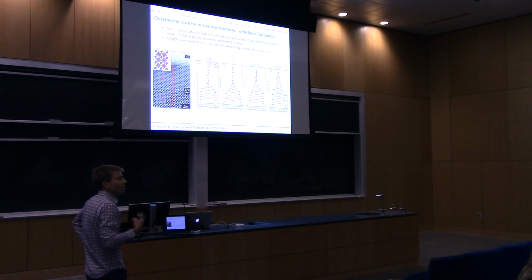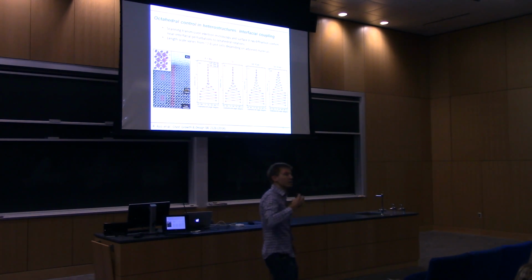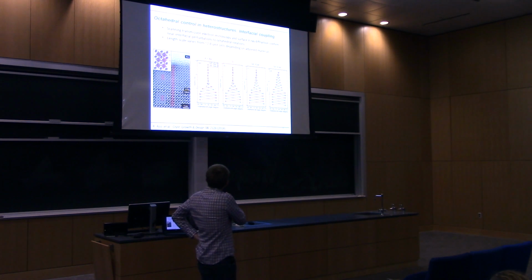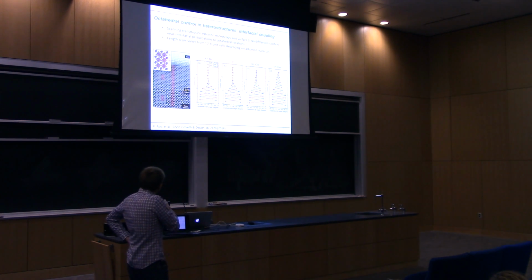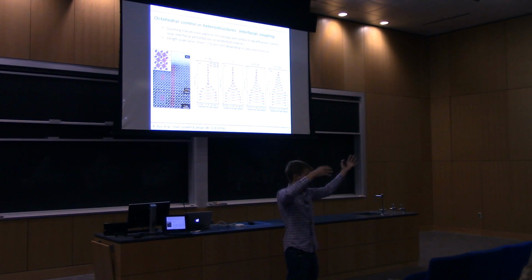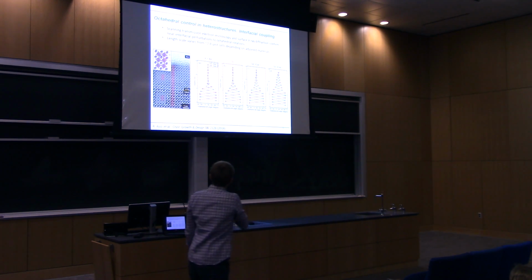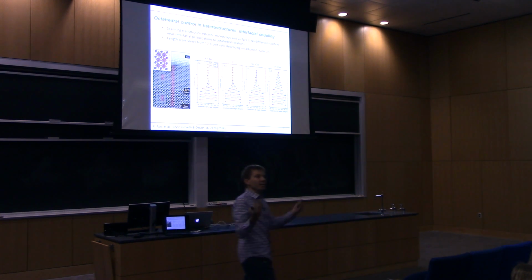Okay, but as I mentioned, I really want to talk about this interfacial coupling. Over the last few years, there have been a number of really nice structural studies, transmission electron microscopy and advanced surface diffraction techniques like COBRA, that have allowed people to map out these octahedral rotations across heterointerfaces. These have shown that as you move from one material to the other, you have this region, as I mentioned earlier, where the rotations go from A to B, and you get something in between the two materials. A variety of these studies have found that this length scale for interfacial coupling is on the order of 2 to 8 unit cells, depending on the adjoined materials, depending on the stiffness of all these bonds.